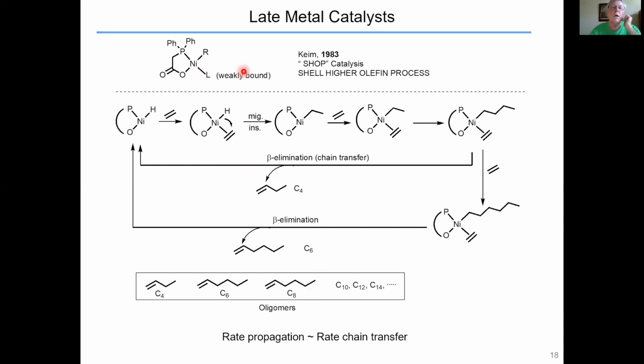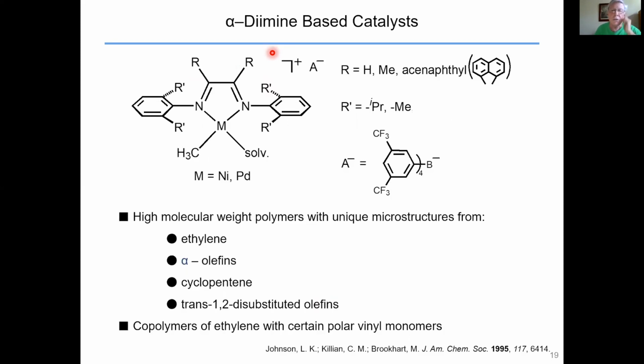These were neutral systems, and we realized that if we had cationic species, they would be much more electrophilic and more likely to exhibit lower barriers to migratory insertion. So to skip ahead a bit, we looked at a number of nickel and palladium systems, and Linda Johnson discovered these alpha diimine systems. So she synthesized a series of these. If you don't have these ortho alkyl or aryl groups on this species, you do generate oligomers, just like the SHOP systems. On the other hand, if you put bulky groups at these sites, you generate high molecular weight polymers, and as I'll show you, they have quite unique microstructures.